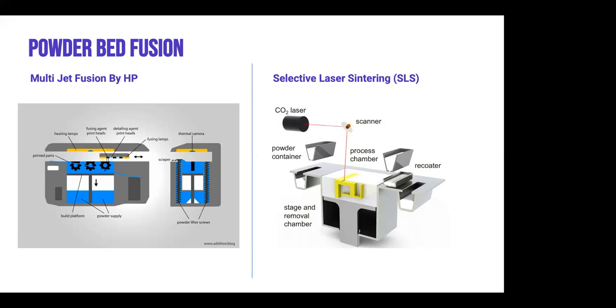However, there are certain differences between the SLS and the MJF. The main difference between the SLS and the MJF is the heat source. SLS uses a laser to scan and sinter each cross section, while in an MJF, an ink is dispensed on the powder that promotes the absorption of the infrared light. An infrared light energy source then passes over the build platform, fusing the inked areas. In the SLS, each cross section is fused point by point, while in an MJF, fusing happens line-wise. This gives a small competitive advantage to MJF, but it does not change significantly the print time, as it is the recoating time that mainly determines the total printing time, which is identical in both of these cases.